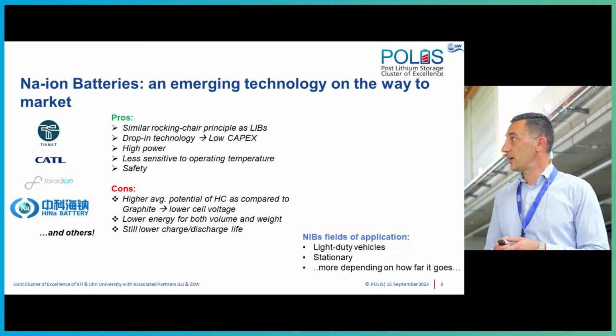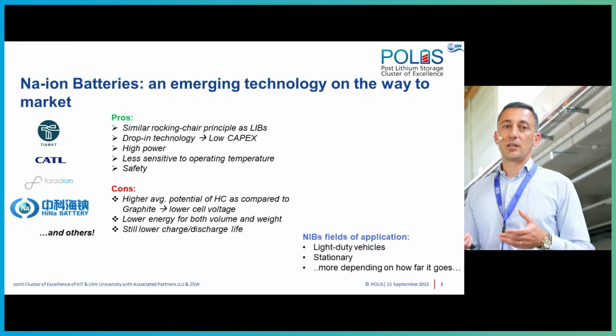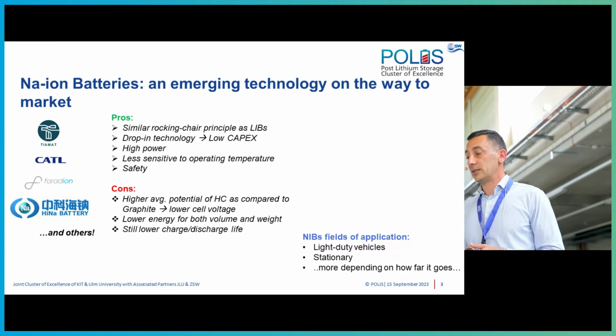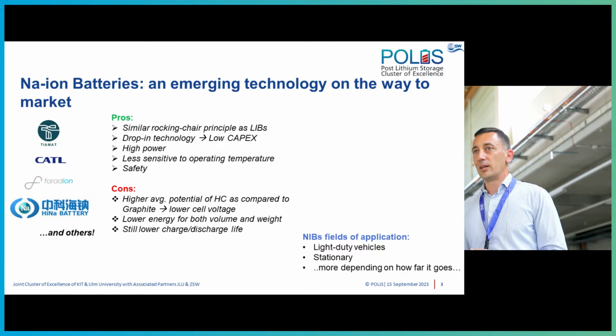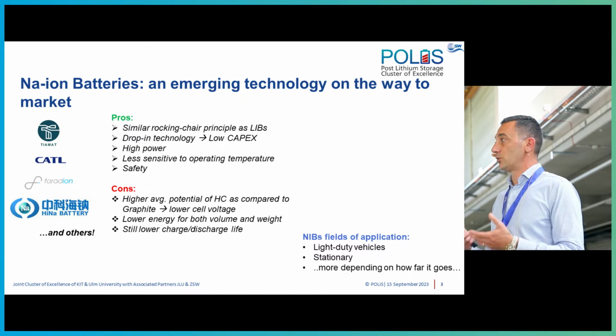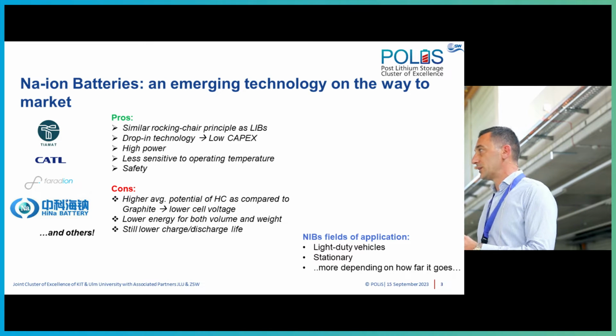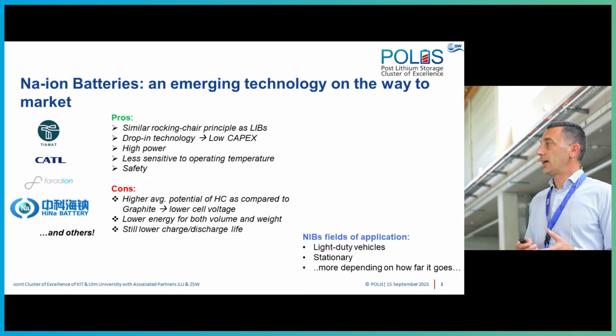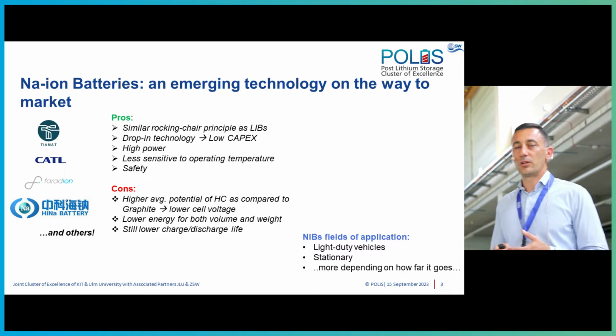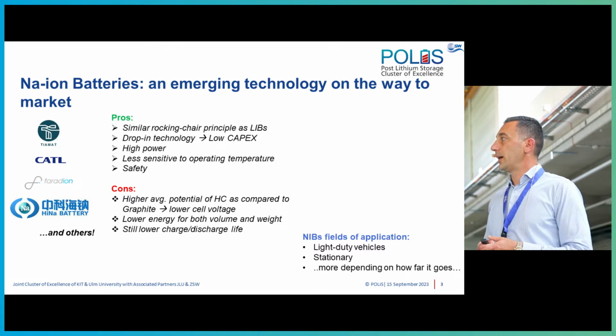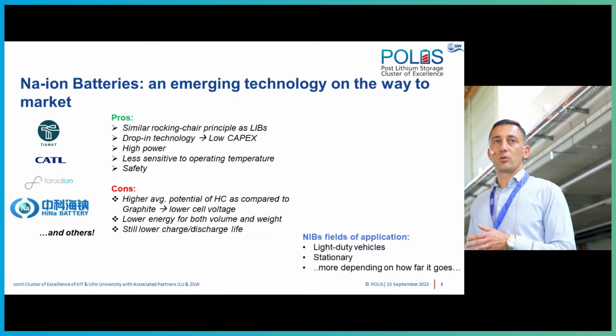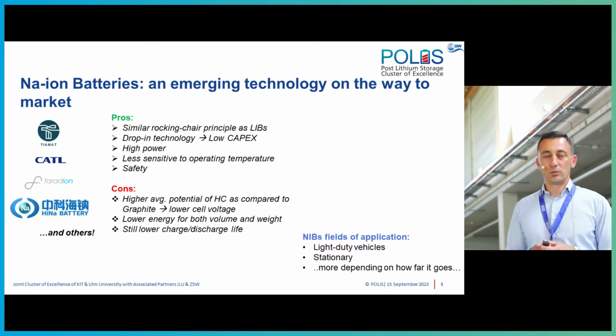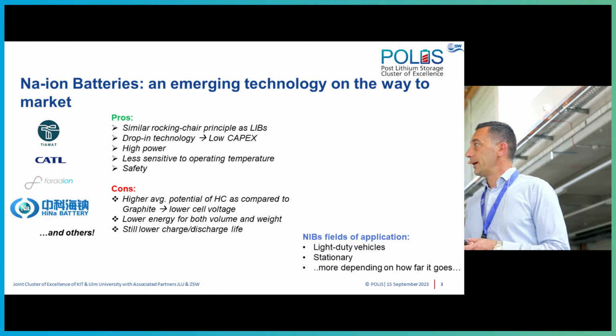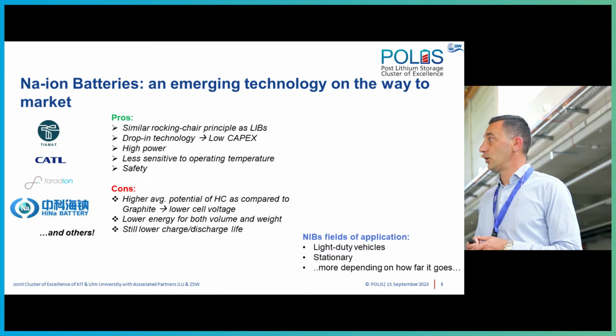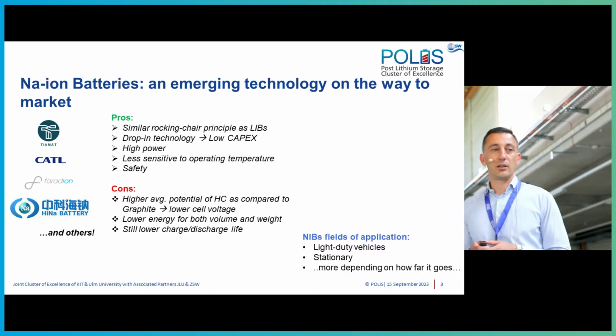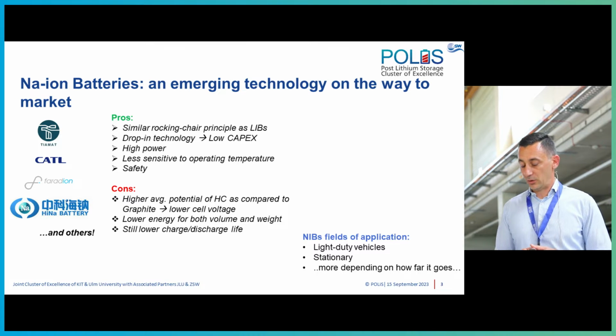On the con side, we have a higher average potential of the hard carbon as compared to graphite. This basically impacts directly the energy of the cell. So at least at the moment, we see that sodium-ion cells have lower energy for both volume and weight as compared to lithium-ion batteries. And of course, still lower charge-discharge cycle life as compared again to lithium-ion batteries.